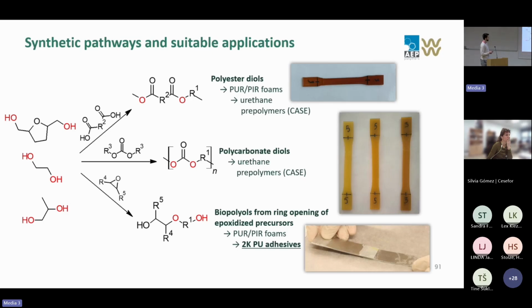For example, in these two pictures, you can see some of the tensile specimens obtained with polyesters and polycarbonates based on BHM-THF, which is this molecule here. While we did not obtain great results with it, it still has a lot of potential for further research. The ones that we mainly employed in the final products were based on these two glycols.